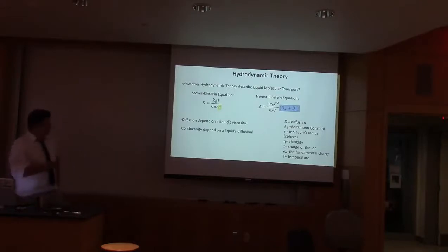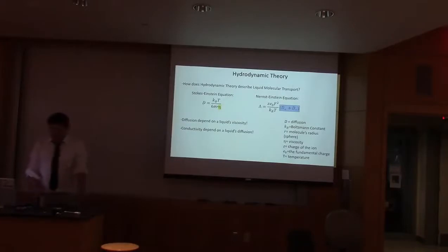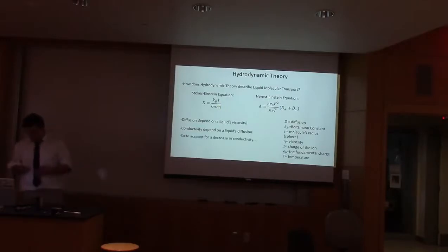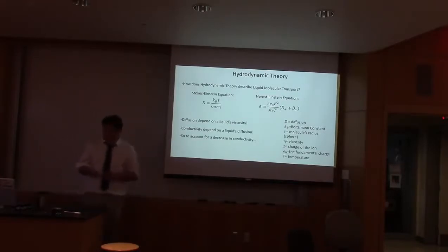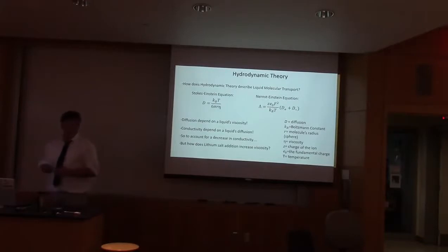This means that the conductivity of a liquid inherently is dependent on its viscosity. So what hydrodynamic theory would say is that this decrease in conductivity that we observe in our room temperature ionic liquids as we add lithium salts to them is caused by an increase in the viscosity. But we have to ask now, how are we increasing the liquid's viscosity? What is causing that according to hydrodynamic theory?